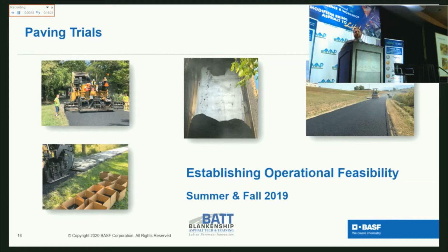And some of the things that we found, it's essentially just anecdotal findings. You can see here with the modified asphalt, there was no sticking to the truck. They used a release agent once in the morning, and they never had to respray the back of that truck with any release agent. It was noted that it compacted easier than their regular mix. So we did have a control, and then our material, and then a control. We basically capped the end of each road with the control, and then in the middle had the isocyanate-based material.